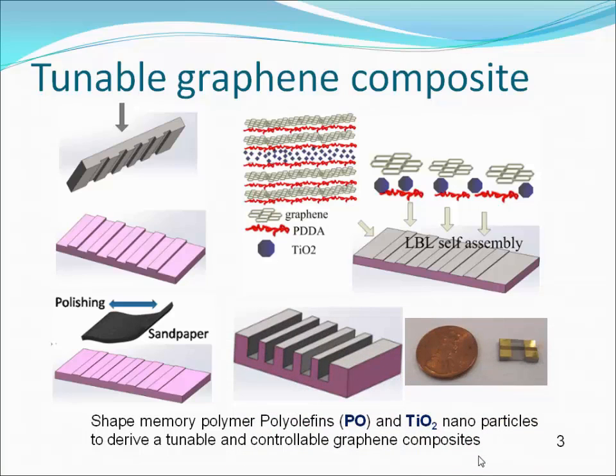And finally, the PO polymer with graphene was heated to desired temperature for shrink. The polymer starts to show obvious shrinkage when the temperature is over about 100 degrees Celsius. Because it's called shape memory polymer, it intends to restore to its original shape. So you can imagine that as a result, the high aspect ratio patterns can be formed on this surface PO polymer. So we can use PO polymer to change and tune the shape of graphene components in this way.